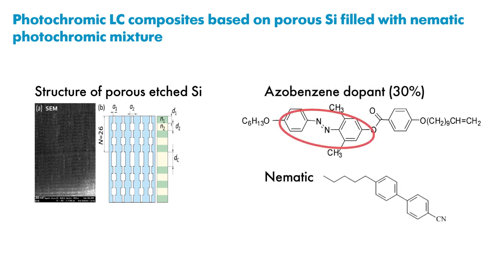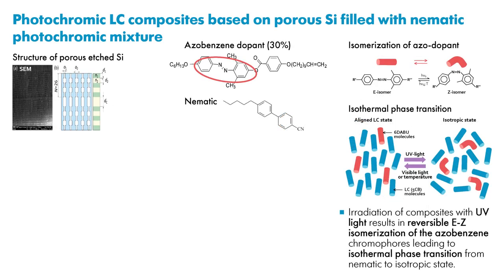In order to realize phototunability of this photonic bandgap position, we have introduced into the prepared porous structure a photochromic mixture based on nematic liquid crystals, pentylcyanobiphenyl, and azobenzene dopant. The main feature of this azobenzene dopant is reversible E-Z isomerization, leading to extreme decrease in molecular anisotropy. Due to this decrease, irradiation with UV light induces isothermal phase transition from nematic state to the isotropic phase.